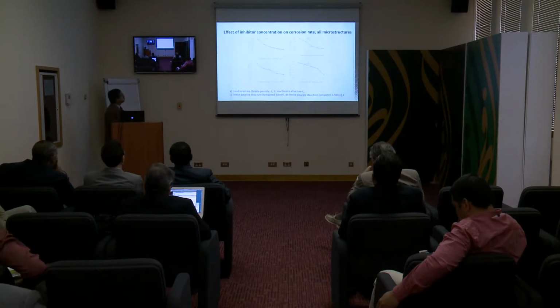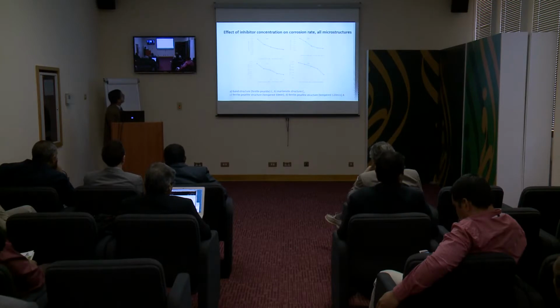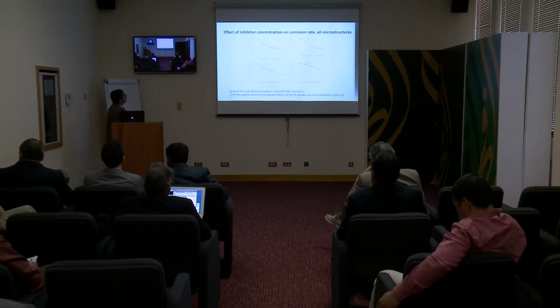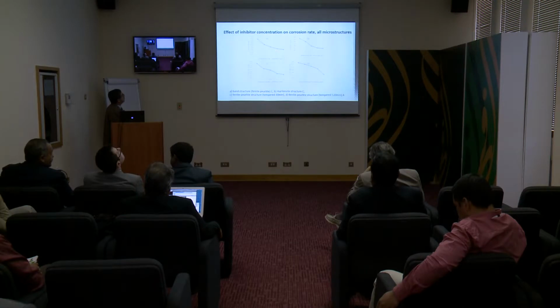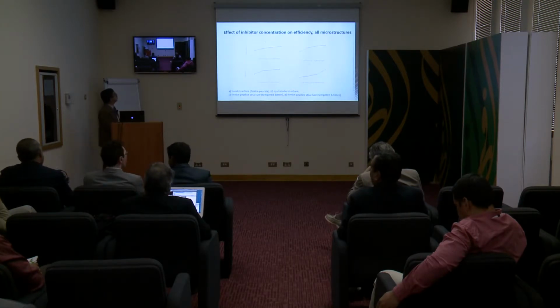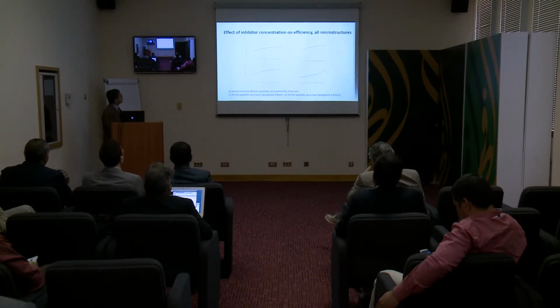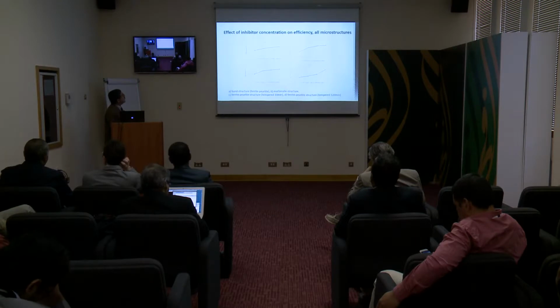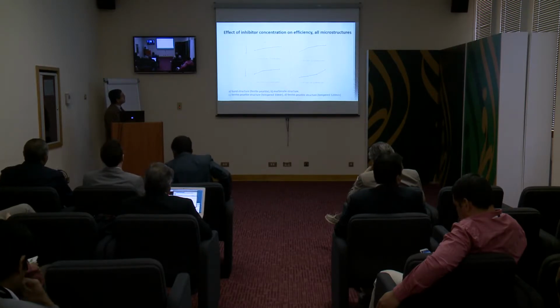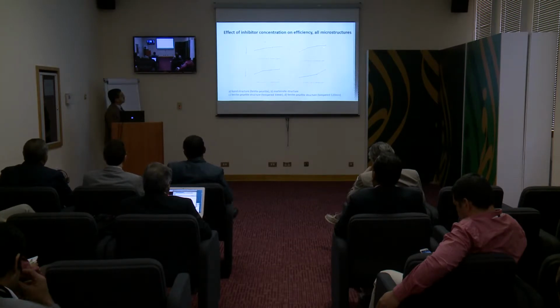For all the microstructures, all the heat treatments, we have a clear effect of the inhibitor concentration. So we have the best results for the higher concentration. Here we put the efficiency, which is the ratio between the polarization resistance without and with inhibitor. And we can see that all the results indicate a good behavior when we put our inhibitor, and we reach values up to 80%.